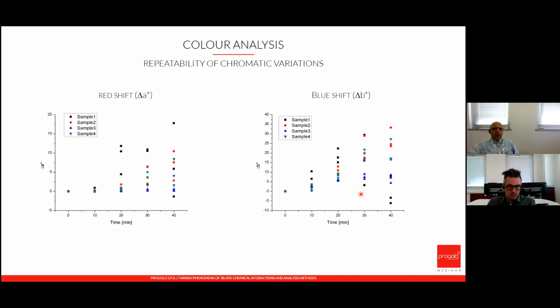By using a digital spectrophotometer to measure the color variation with respect to the starting hues, and following the CIELAB procedure that was extensively described by my colleagues during a previous webinar, the averagely most resistant alloys were silver-plated sterling silver and commercial alloys, as depicted by the red and the blue components shift along the ordinate axis as a function of time.